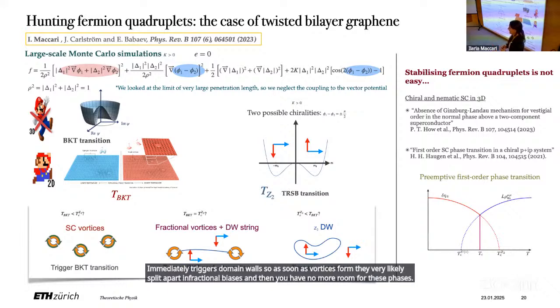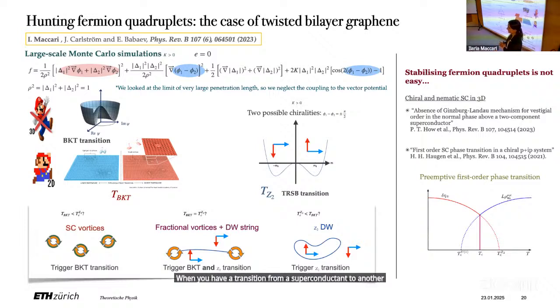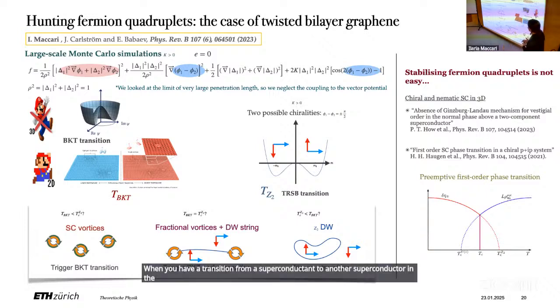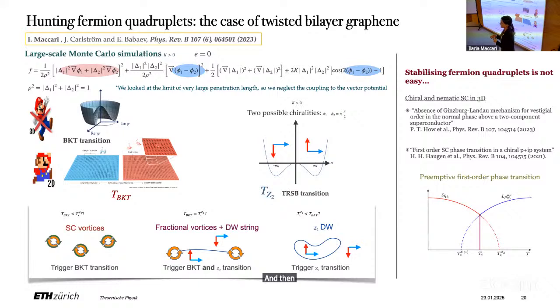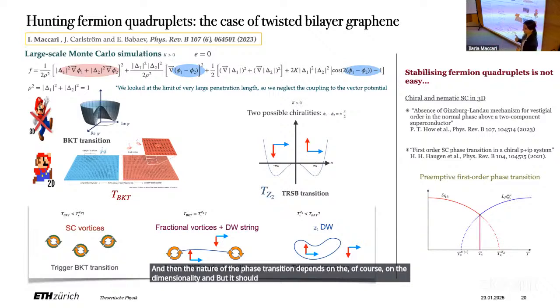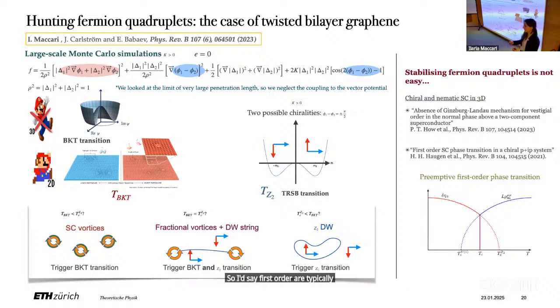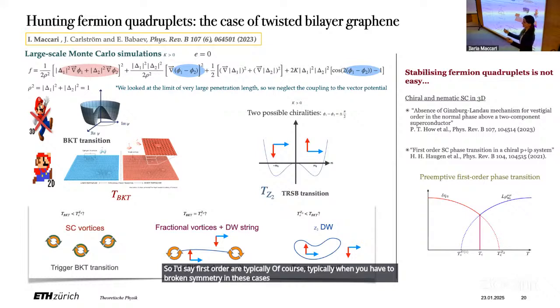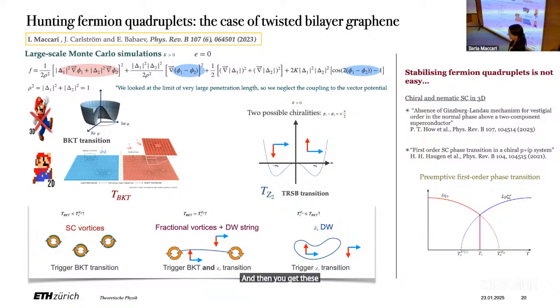When you have a transition from a superconductor to another superconductor, from the perspective of the fermion quadruplet, I can imagine it maybe with respect to the charge 4e superconducting state, where you go from a superconducting state to another superconducting state. And then the nature of the phase transition depends, of course, on the dimensionality, but it should be driven by phase fluctuations in any case. So let's say first order are typically, of course, when two symmetries get spontaneously broken at the same time, and then you get this kind of signature.